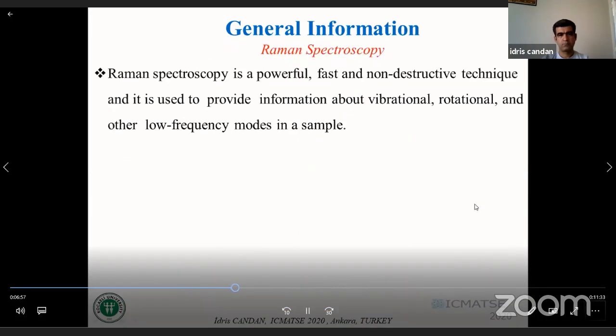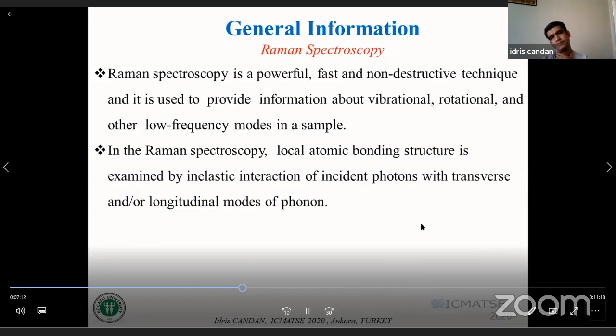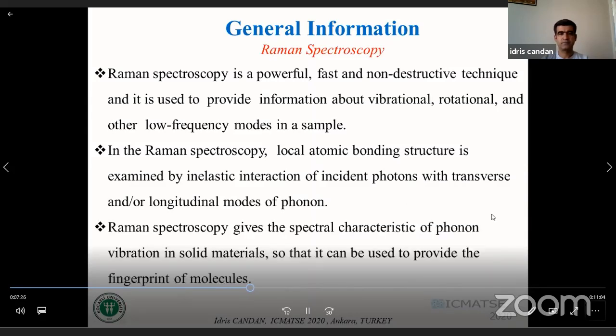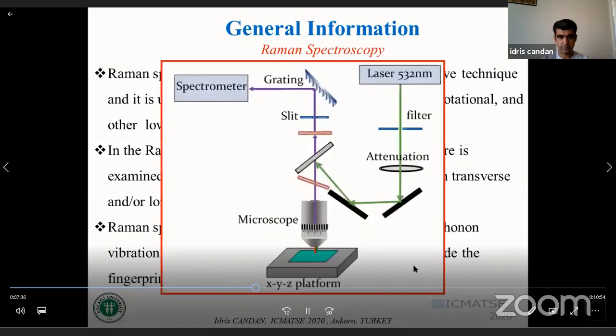And Raman spectroscopy is a powerful, fast and non-destructive technique, and it is used to provide information about vibrational, rotational, and other low frequency modes in the sample. In Raman spectroscopy, local atom bonding structure is examined by an inelastic interaction of incident photons with transverse or longitudinal modes of the phonon. Raman spectroscopy gives the spectral characteristic of the phonon vibration in the solid material so that it can be used to provide the fingerprint of the molecules. Here you can see the schematic illustration of Raman spectroscopy.